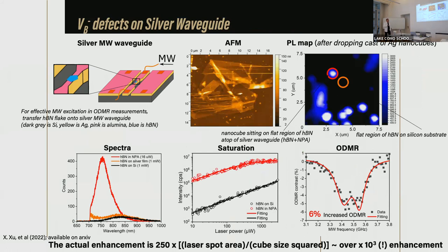But it's made of silver, and if you just scatter silver cubes on top, so you have the flake sitting on a silver waveguide, and you spread the silver cubes. In some cases, a cube sits right on top of the flake, and underneath you have the silver waveguide. You could see that indeed photoluminescence is dramatically increased. This is actually at much, much lower pump than in the case when your flake is sitting on silicon.